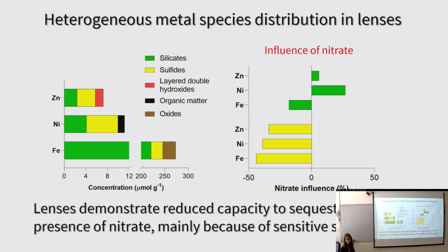of sulfide formation. And these results here show us that the presence of nitrate is essentially resulting in a reduced capacity of these lenses to retain heavy metals, most likely because of a sensitive metal sulfide pool that appears to be most sensitive to groundwater composition and oscillations in redox conditions.